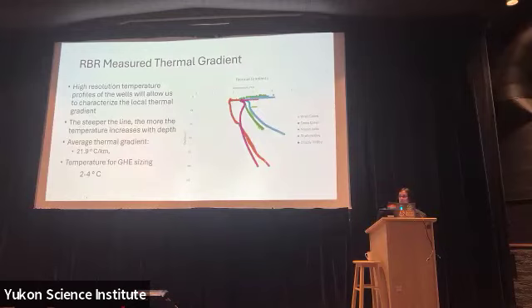And then you're seeing the thermal gradient that is increasing with depth, because I think the global average is about 25 degrees Celsius per kilometer. As you're going down, your temperature is increasing. So the steeper the line, the more the temperature is increasing with depth. So within these 5 wells that I've measured, the average thermal gradient was 21.9 degrees Celsius per kilometer. The measured average for Whitehorse in deeper wells, like going to 500 meters depth, is actually between 26 and 28 degrees Celsius per kilometer. So that line is increasing the deeper that you get. And we're using a temperature between 2 and 4 degrees Celsius for the ground temperature parameter that goes into the sizing of the ground heat exchangers.